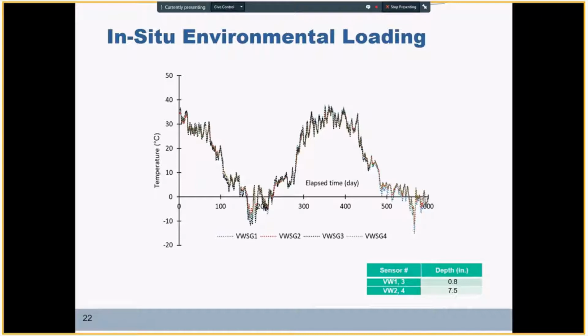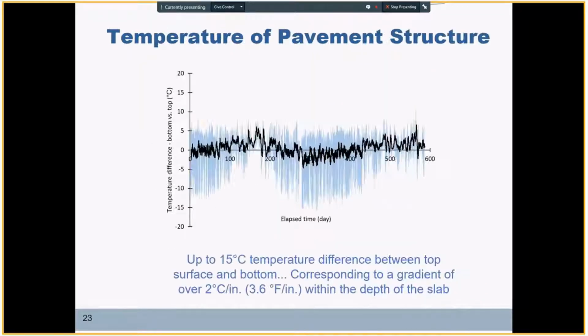We have 4 sensors per concrete type per cell, monitoring variations in temperature at depths of the slab, and we can determine the thermal gradient for the slabs. Here, for example, I have data for cell 238, where we see a temperature gradient of up to 2 degrees centigrade, i.e. 3.6 degrees Fahrenheit per inch over the depth of the slab. Such thermal gradients cause deformations in terms of warping.